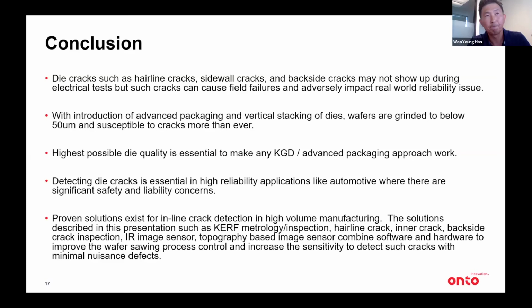In some cases, it works. That would be real big cracks. So very large cracks can be detected that way. A lot of hairline cracks or a lot of cracks that happen underneath the die surface don't show up. We cannot find cracks that way, because if you look at them from the top, they all look good. Seems like there's a common thread here among a lot of presentations. It depends. Sure, yeah, so it depends.